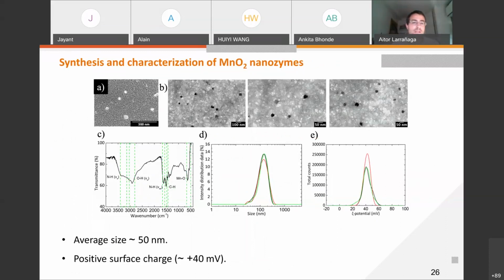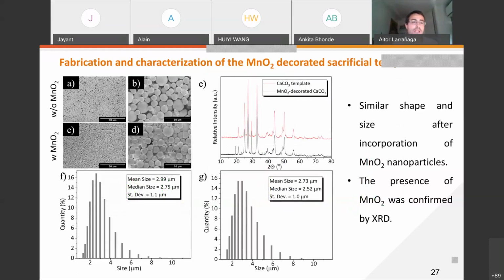So then we incorporated these positively charged manganese dioxide nanoparticles in our negatively charged calcium carbonate sacrificial template by simply mixing both solutions and allowing the electrostatic interaction to happen. If you look at this scanning electron micrograph, you can see that we didn't find any big difference in the size or the shape of the sacrificial template before or after being incubated with manganese dioxide nanoparticles. And when we check the size distribution that you can see below, we didn't find any big difference between the calcium carbonate particles with or without the manganese dioxide nanoparticles. In all the cases, the particle size was around 3 microns.